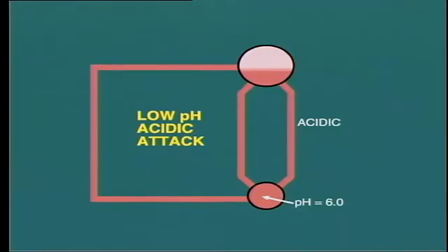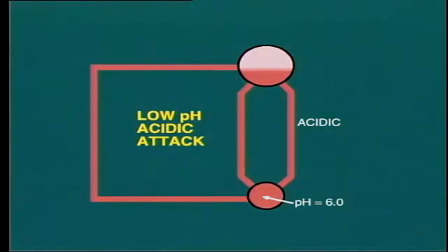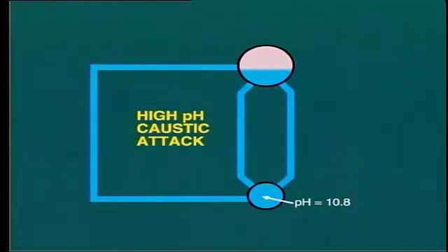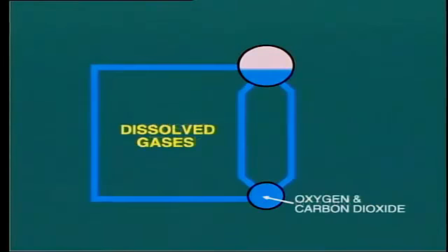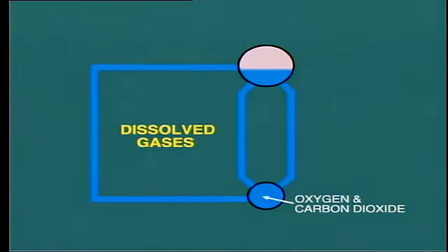So what are the conditions that cause corrosion and loss of metal inside the boiler drums and boiler tubes? Well, there are basically three independent causes of corrosion, and they are acid attack, which occurs when the boiler water is in an acidic condition, that is, low pH. Caustic attack, which occurs when the alkalinity of the boiler water is too high, the pH level is above about 10.5. The presence of dissolved gases such as oxygen and carbon dioxide in the boiler water.